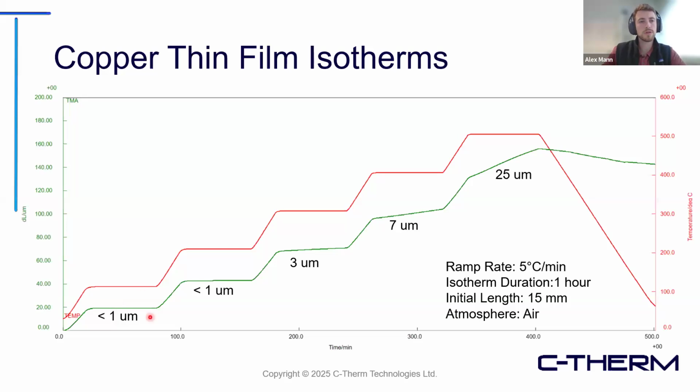You're not increasing the temperature, you're not seeing expansion. That's what we want, that's what we expect. Up around 300, even though we weren't increasing the temperature, we started to see some expansion. Then up to 400, we saw that even though we weren't raising the temperature, we're seeing a lot of expansion, and then the same as we go up here.